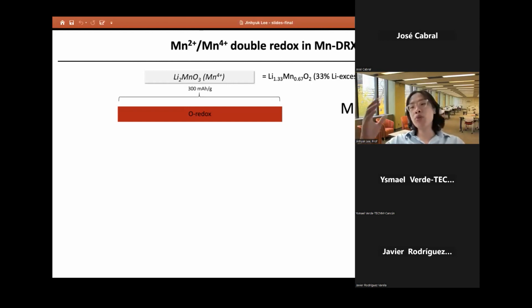So the diffusion through the zero-TM percolation may be fine. But now if you look at the manganese oxidation state, it is already manganese 4+ at the discharge state. And in this kind of oxide structure, manganese 4+ is considered the highest oxidation state that manganese can take. So if you want to extract all this lithium from the Li2MnO3, you can never get any electron from the manganese oxidation. So you basically have to completely rely on the oxygen oxidation process, right?